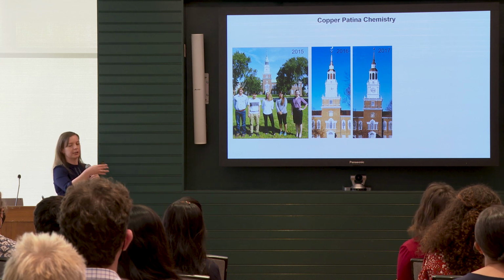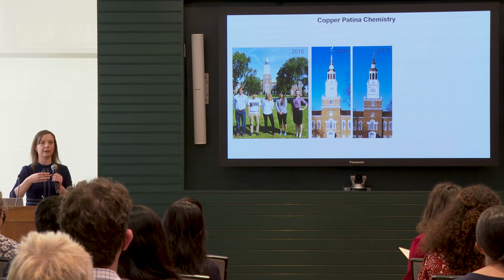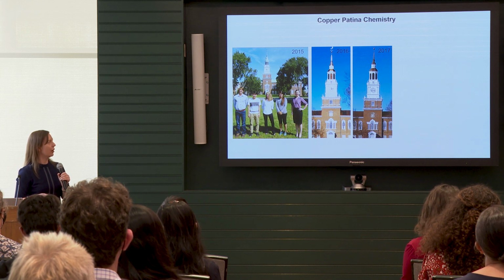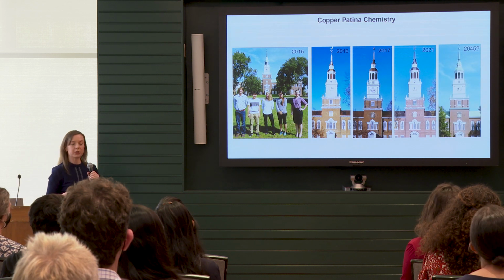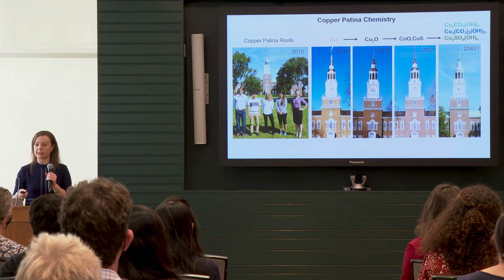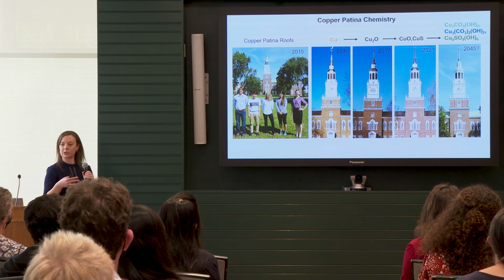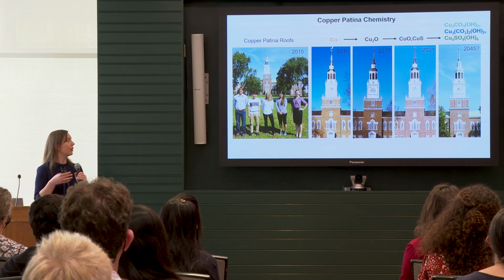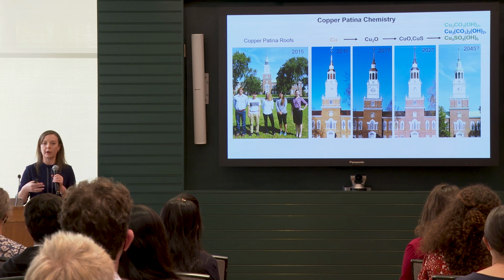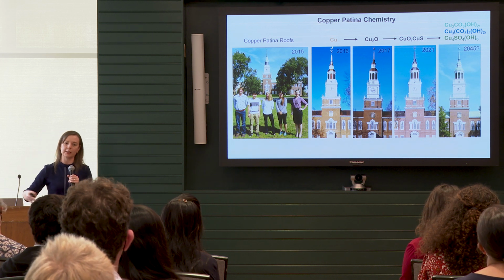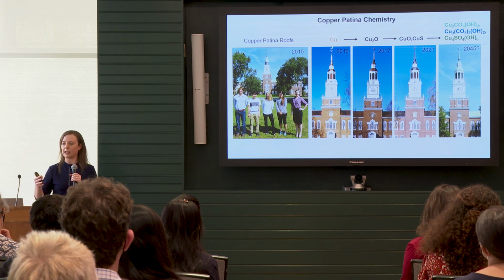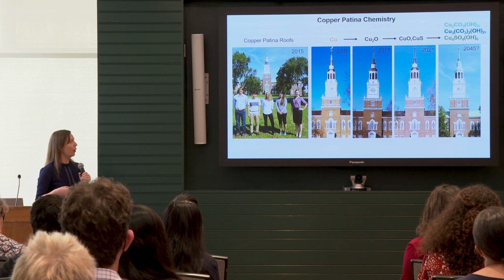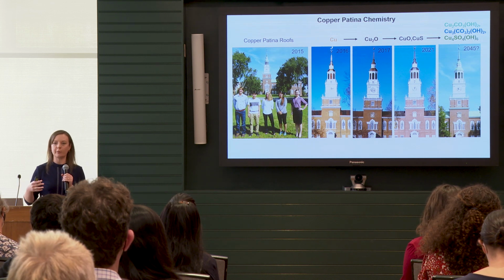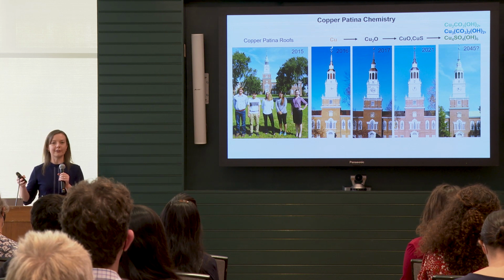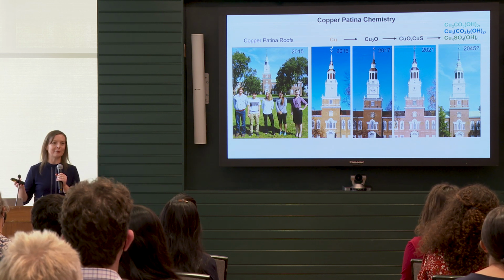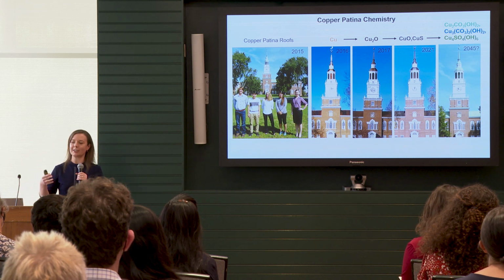So in 2016, kind of 2017, after a few months of that transition, we've gone into a copper oxide phase, but there's a number of copper oxides that exist. So the first oxidation process gives a copper(I) oxide, so it's a +1 copper oxidation state, and then further oxidation processes go on, and the material settles into a copper oxide or copper sulfide, so CuO or CuS, depending on how much pollution and sulfur is in the area. We have excellent air quality in Hanover, so this aging process might take some time.